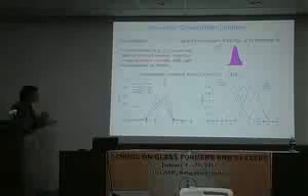So the red line here, the dots, are for SiO2. And you see that for this simple glass former, all silicon atoms have exactly 4 nearest neighbor silicon atoms. Because we have this tetrahedral local structure, and you see it right away without measuring anything complicated, that this is a tetrahedrally coordinated system.